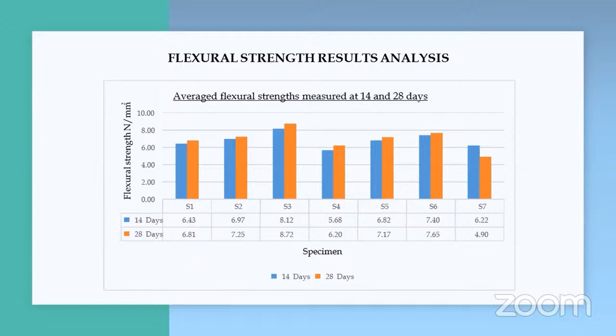Calcium silicate hydrate primary gel and calcium hydroxide are formed when cement reacts with water. Moreover, RHA produces calcium silicate hydrate secondary gel when silica reacts with calcium hydroxide. Calcium silicate hydrate is the governing compound that contributes to the strength of cement mortar, whereas the compound calcium hydroxide had a negative impact on the cement mortar strength.